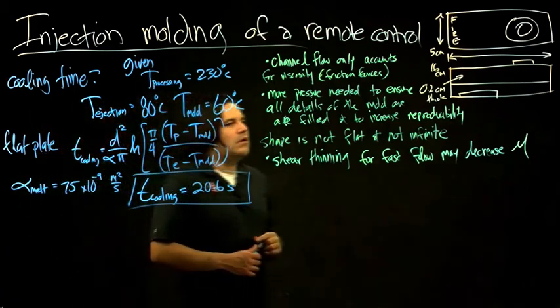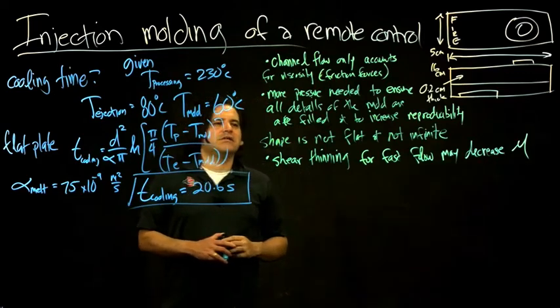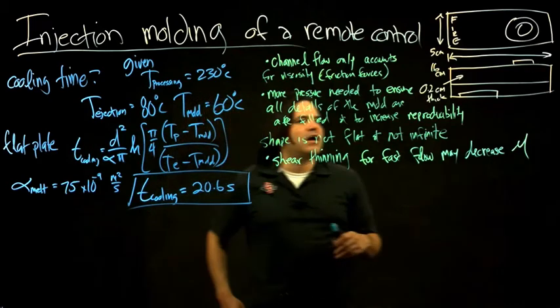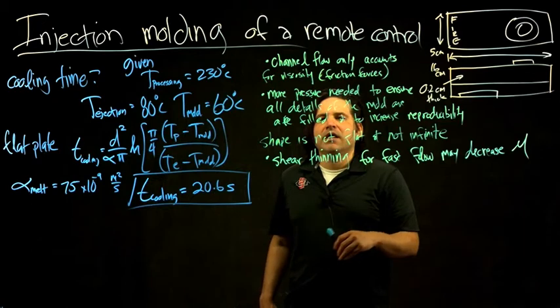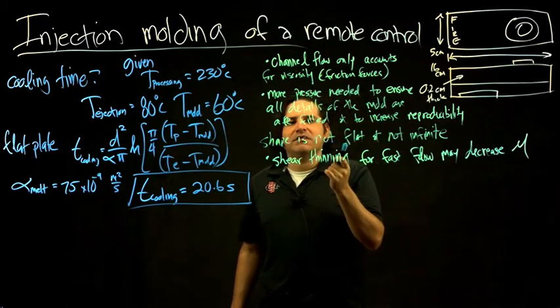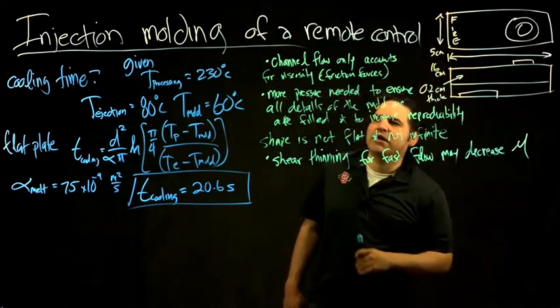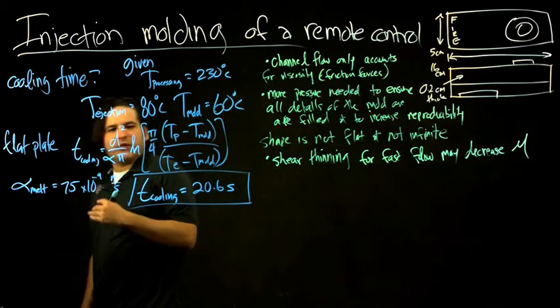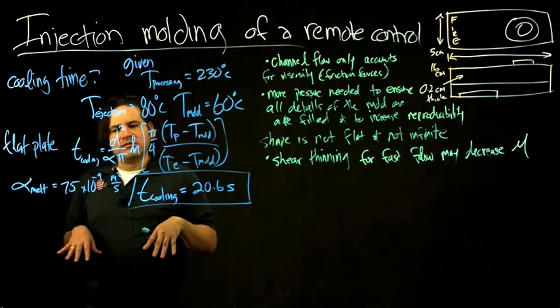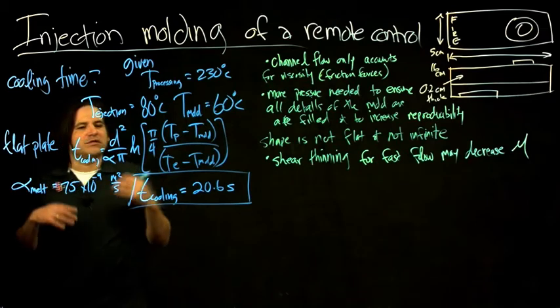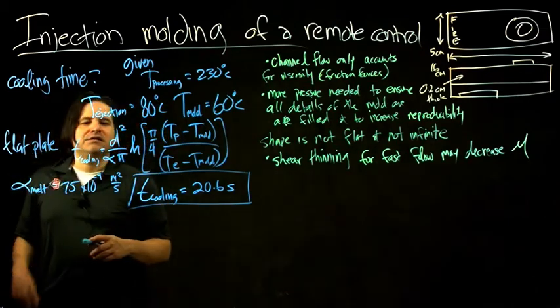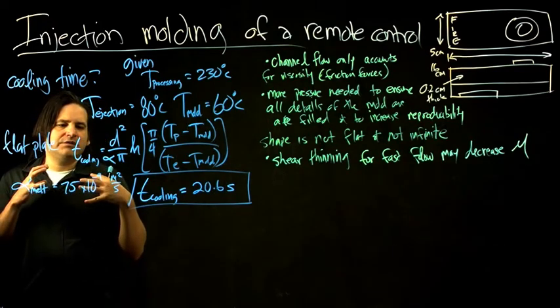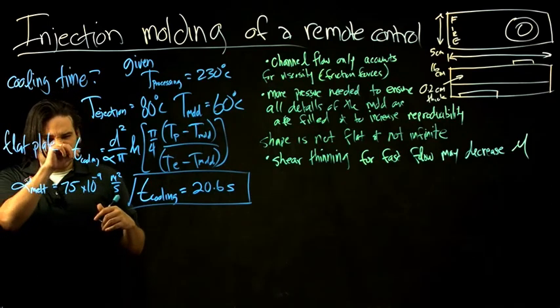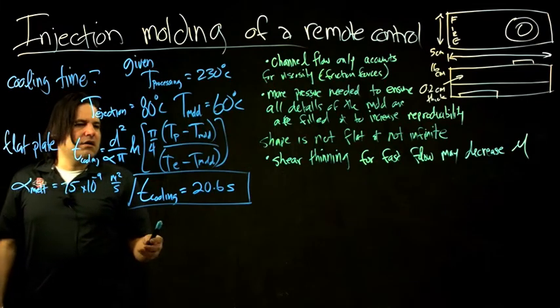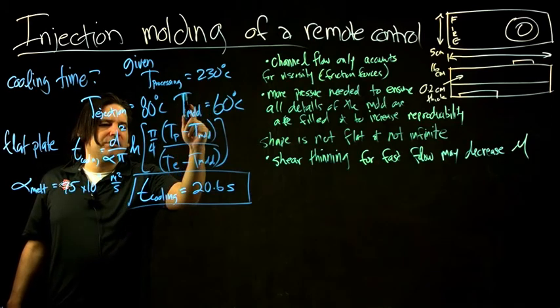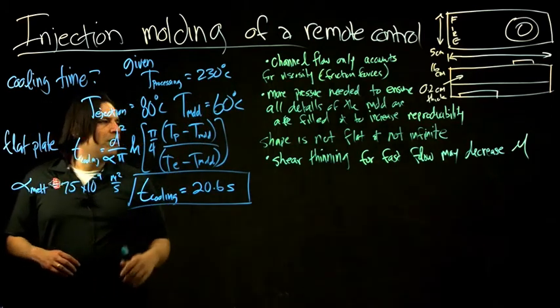So that is a simplified analysis where in both cases we did not consider the complex geometry that many parts have. For the injection pressure, we simplified it by using this flat plate. And then we had these viscosity relationships, which we had to simplify, and the fact that you're injecting into some features adds more viscosity. So that was the minimum pressure drop. Here, we're also doing a simplified analysis. We're saying that for this flat plate, solving these governing equations, you can estimate based on a simplified expression for the energy equation, given these processing temperatures and the ejection temperature. So it gives us a ballpark of around 20 seconds.